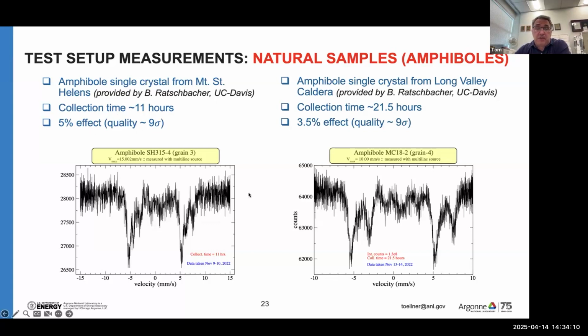These are, like I mentioned, very low concentration. I don't know the weight percent offhand, actually, but I just know there's very little iron in them. And of course, it's natural, so it's 2.2% isotope abundance. But if you convert this to the new instrument, assuming a 3 gamma line width, the 11 hours would turn into 11 minutes. So that's the quality you would get after 11 minutes.